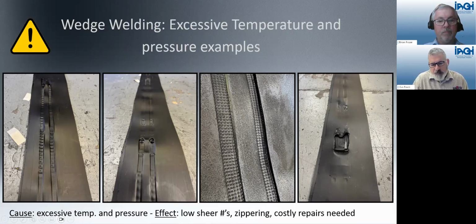The next picture to the right is too much pressure, too much heat, and or too slow, which leads to a burnout and improper welding practices. The next picture to the right shows too much heat, too much pressure, and I'm guessing too much overlap on the top sheet, which pushes the top sheet over, which compromises your weld, which results in low shear numbers, peel, bad welding practices. And the last picture on the right is a straight burnout.